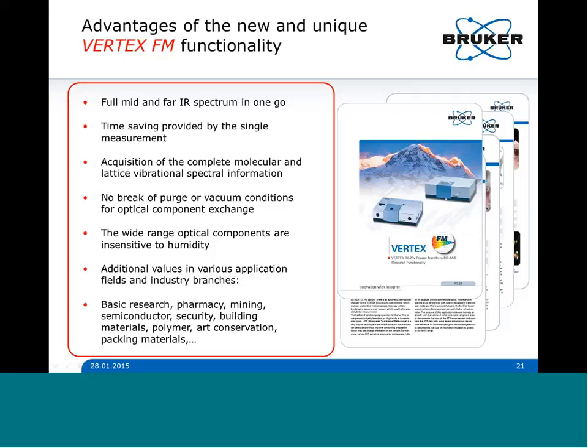Okay. Now we have one attendee who is asking about the achievable resolution of the wide range beam splitter, and if it's possible to measure a resolution of half a wave number. Well, half a wave number is still possible. The best achievable resolution using this wide range beam splitter is 0.4 wave numbers, and that is actually more than enough for all condensed phase samples, and also for gas samples under normal pressure.